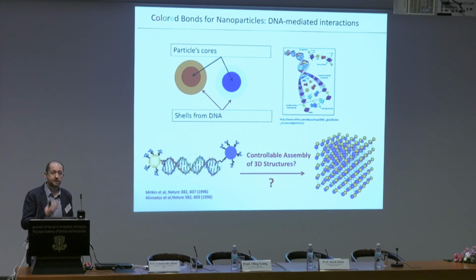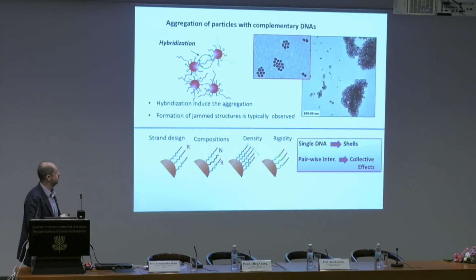So part of my talk, I will discuss really what is important. When we started doing this work, yes, you can create particles with DNA grafted to them. However, typically you would observe some kind of non-specific aggregation. The reason was that it's not only driven by pairwise interactions between two DNA from two different particles, but there are more complicated effects, due to this shell structure determined by the composition of the shell, the rigidity of DNA, and so on. From the interaction point of view, it's not really pairwise anymore. There are different collective effects, even many body effects, when more than one particle comes to interact.